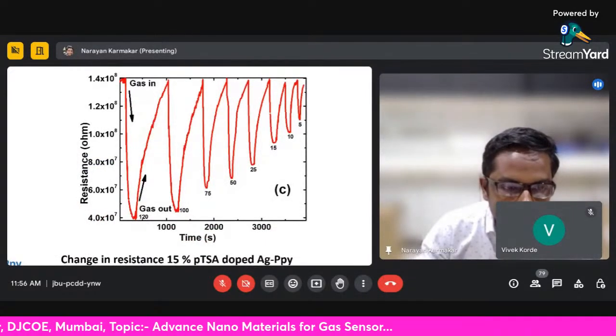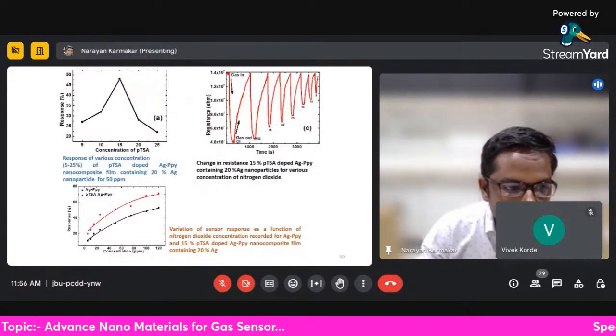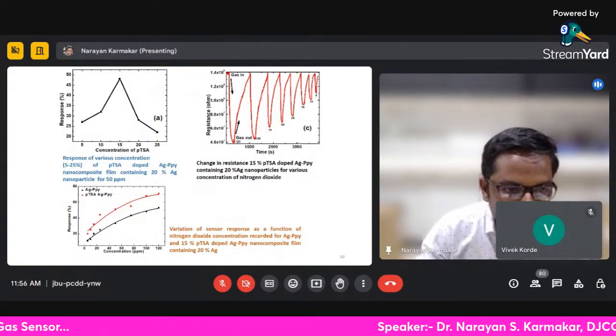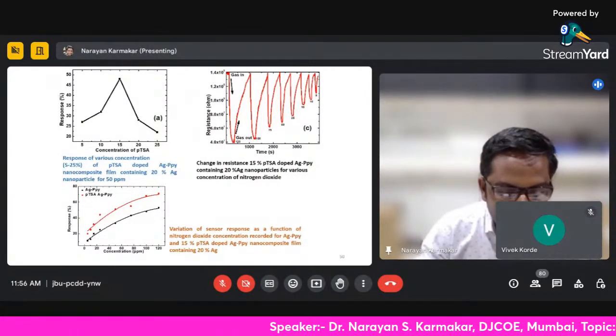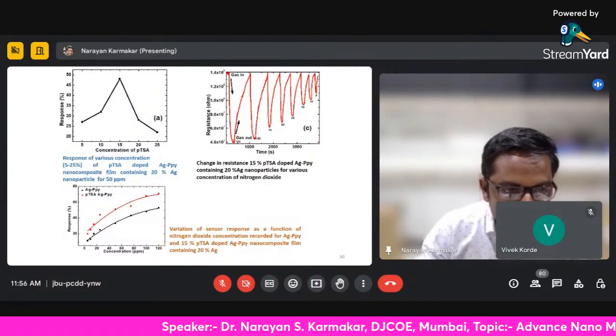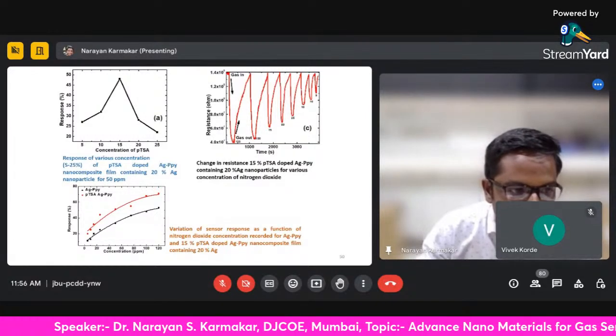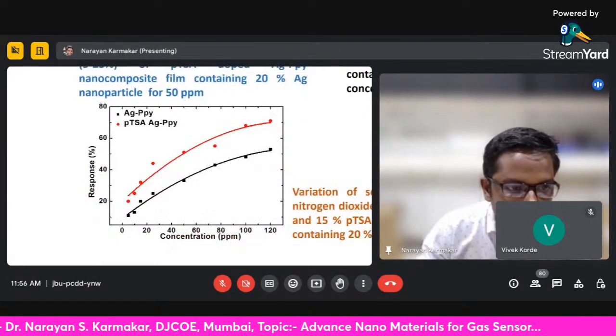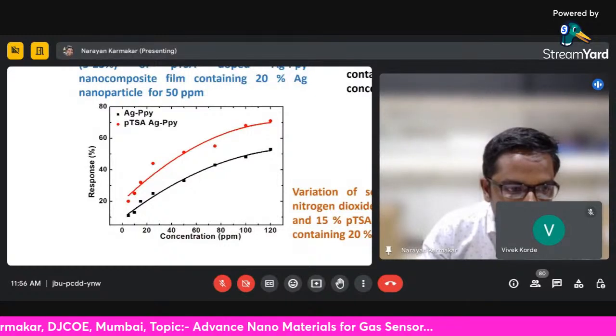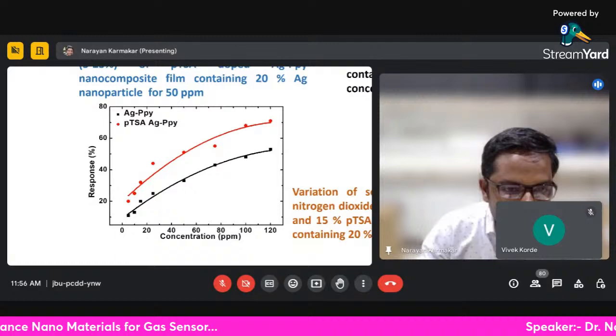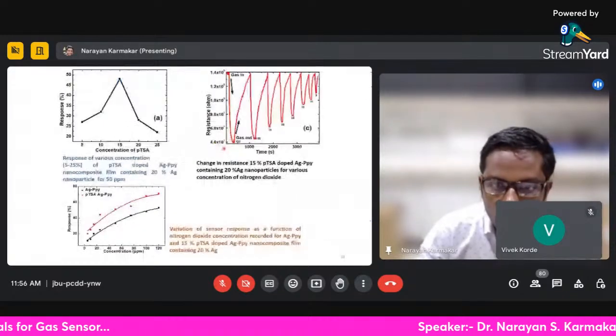This shows a comparative study of the sensor response as a function of nitrogen dioxide concentration, comparing AgPPy and PTSA-doped AgPPy at 15%, where you can clearly see that the response to this gas is overall improved.